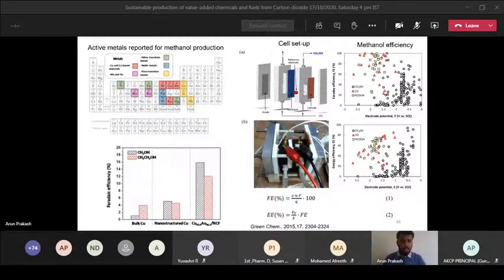And with methanol and ethanol, you can observe different materials like bulk copper. The methanol selectivity is very poor. That's why people try to develop nanostructured copper, and alloys like cobalt, gold, and nitrogen-based carbon fibers can yield higher Faraday efficiency. Basically, instead of having a bulk material, if you have a nanomaterial, you can achieve higher CO2 reduction efficiency. But for selectivity, you have to consider the adsorption energy for proton, carbon monoxide, and also hydroxyl ion.